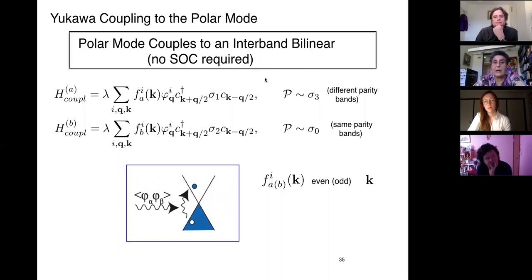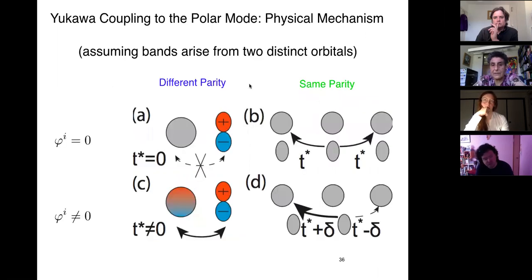And there are a couple of polar metals that are multiband. Here, the polar mode couples to an interband bilinear, and no spin orbit coupling is required. If we think of the parity operator in two bands, time reversal is like complex conjugation. Parity operator, if we're operating on band space, here we have different bands, and here we have same bands. We're interested in interband bilinears, and here this will be even, this will be odd, and let me just give you a physical picture of how this can happen.